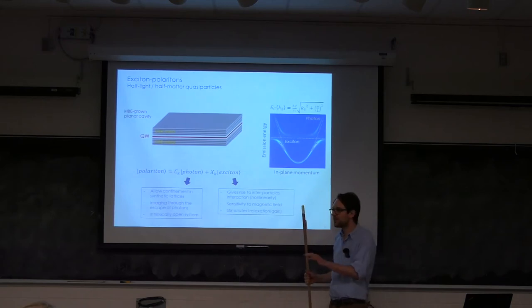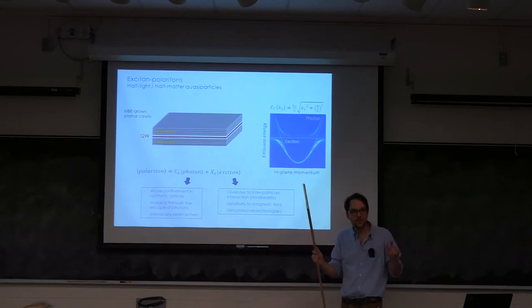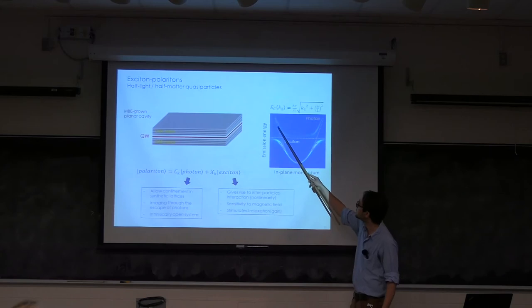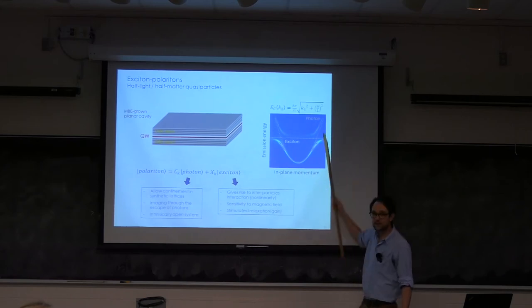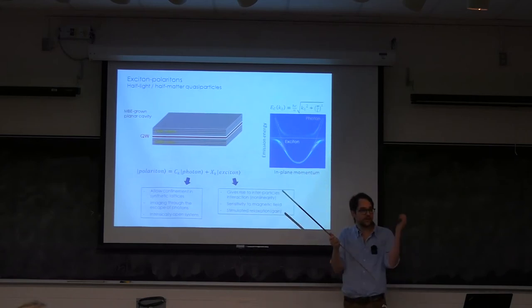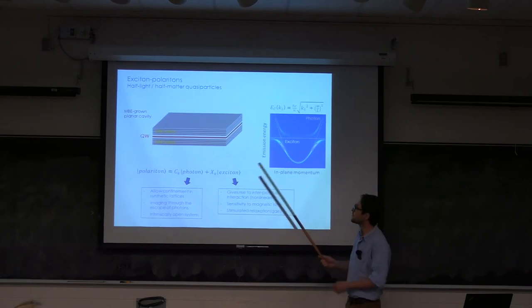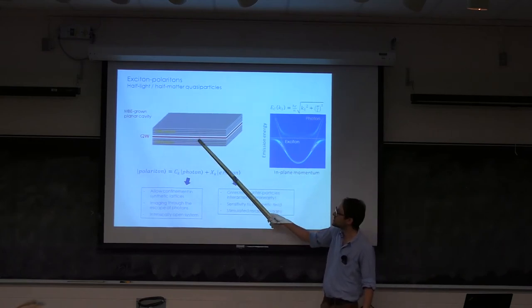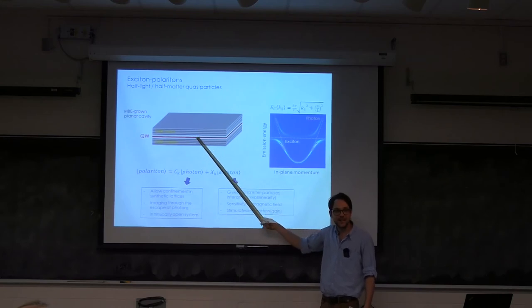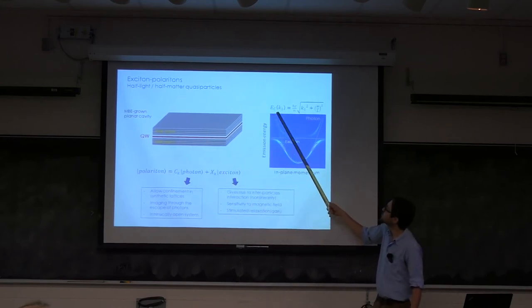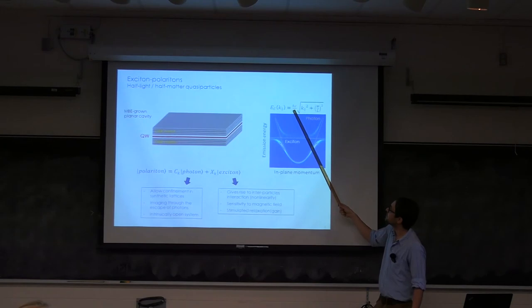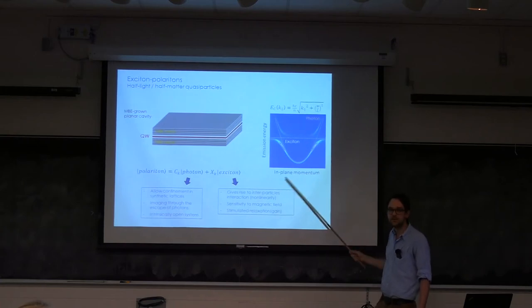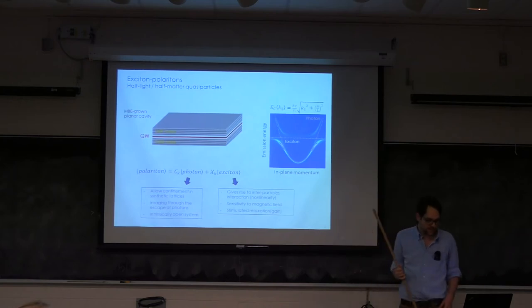So I'll just take a small moment here to do a small parenthesis. You might wonder why we have this parabolic dispersion for photons rather than a linear dispersion. And this comes from the fact that our cavity breaks translational invariance along the z-axis. And so the energy is ħc over n times the square root of k parallel squared plus something that is confined here. So if you expand this around k equals 0, you really have a parabola. This is where it comes from, so there's no issue here.